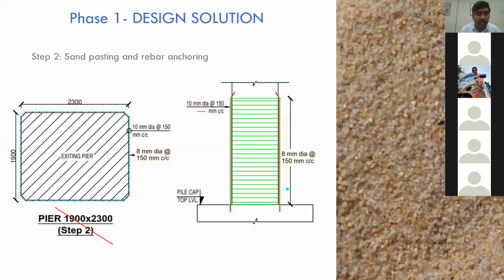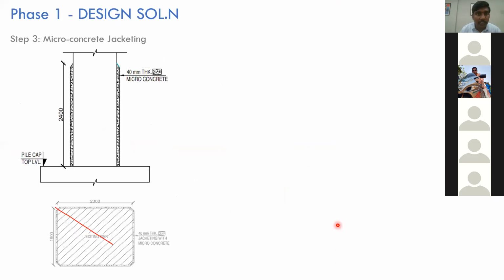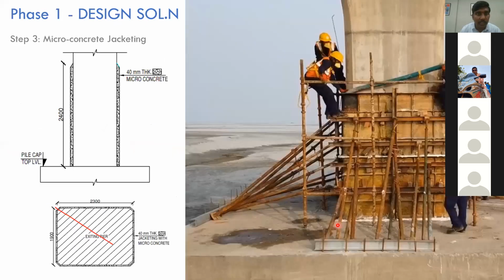you paste washed silica sand on top of the surface of the FRP like this. You can see, and this is for providing the grip. Okay, grip into what? Because we are doing microconcreting. So we have a 40 thickness microconcrete, which you can see is being poured into the pier. So for the microconcrete to have a bond with the FRP that is inside, you applied the sand layer. This is for shear strengthening of this project.